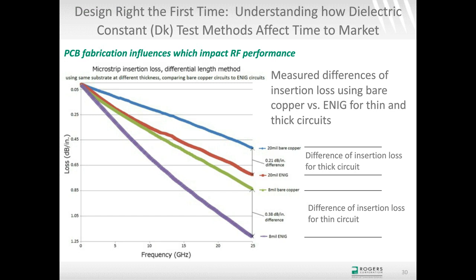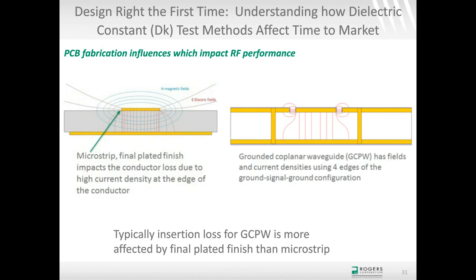So there is a design dependency to the influence of these plated finishes, and a lot of times I'm asked why microstrip is affected by these different plated finishes when most of the fields are between the signal plane and the ground plane, and at that interface, these plated finishes do not have influence. So the plated finishes are actually on the sidewalls of the conductor and the top of the conductor. But if you look at electromagnetic modeling, you'll find that at the corners where the conductor meets the substrate, there is high current density and there are strong electric fields. And it's that corner effect that actually increases the losses due to a reduced conductivity of the metal finish. So it's really a corner effect at the corners of the signal conductor meeting the substrate.